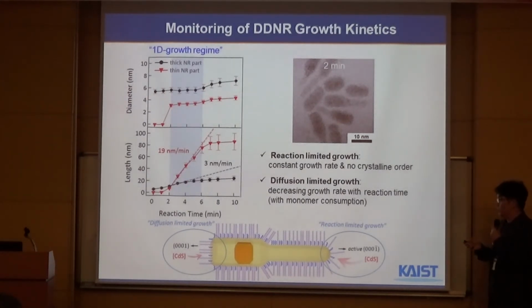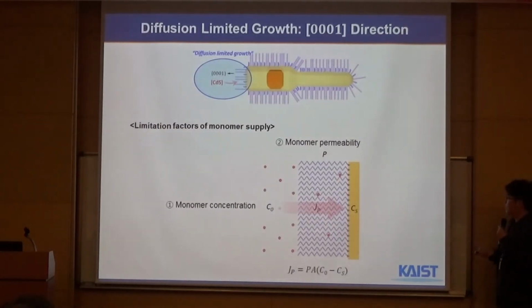And as you can see, the beauty of this approach is to be able to measure the length over time and record it, and then get this time scale or growth rate scale, without having to take samples over seconds or milliseconds. You can do this by taking samples out of the reaction every minute or every 2 minutes, and then you will be able to see how fast it grows in one direction versus the other.